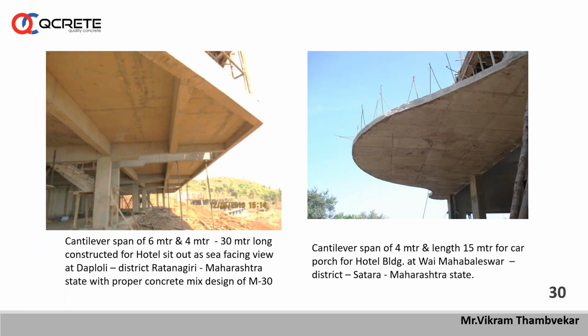See another picture here. This is a big building I have shown here, with cantilever spans of 6 meters and 4 meters. This hotel or resort building is coming up very close to the sea. The sea is hardly 500 meters from our site, and these structures are on a hillock. This bigger cantilever happened because of changes in design. So instead of providing an additional column, we went straight to the cantilever structure. The grade of concrete used is only M30. But you can see the finishing of all these formworks is very fine, and after de-shuttering, removing all the props, everything is fine. The age of this structure today is about 1 year. Nothing is wrong, nothing has happened to it.